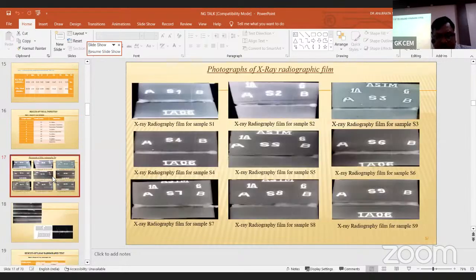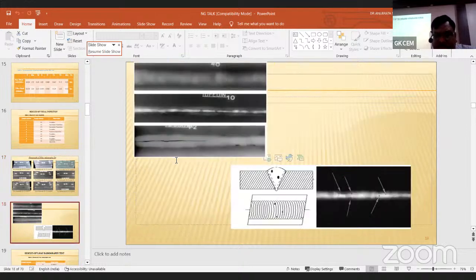Have you seen the X-ray radiography film of any welded part? This is the X-ray radiography film. Here, many types of defects like porosity, lack of fusion, lack of penetration, and undercut have been shown in this slide. But unfortunately, in all these 9 sample experiments, no such defect has been found. But in the next slide, we can see a defect like lack of fusion.